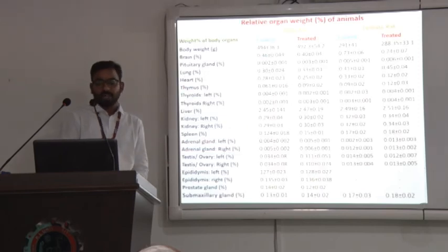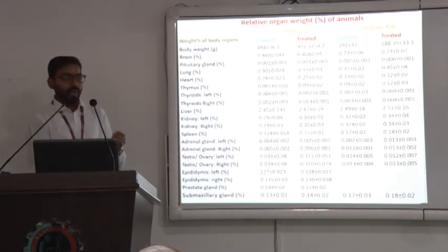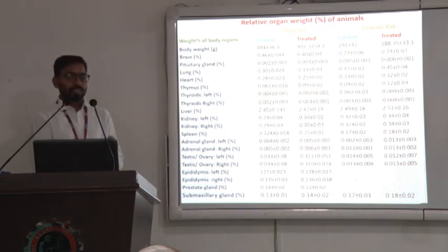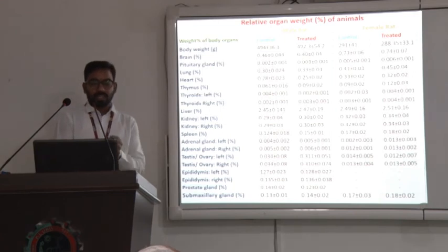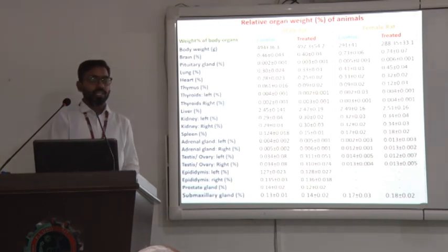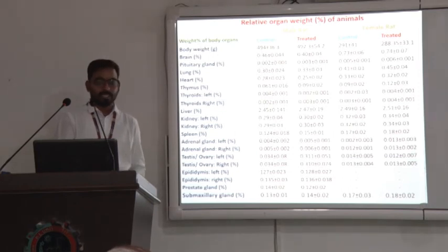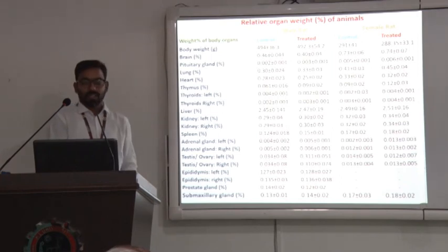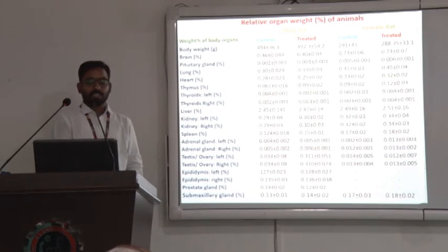These are the relative organ weights. After the experimentation time of 90 days was completed, we measured and observed the body weight and whether any defects or any body part damage was caused by the metallic sample inserted into the rat. They are compared with the control rats for male and female rats. We can see that there is no significant difference between the control and treated rats.